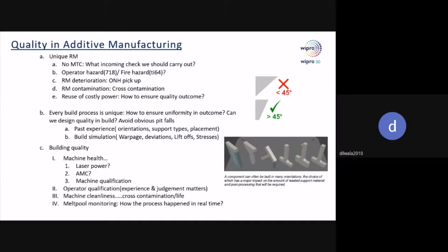Then creating additional supports or placing the parts fully. Like I said earlier, you can fill the build plate with parts fully. What will happen? Then the area of exposure would increase. When the area of exposure increases, there is a possibility that you will get more warpage and more distortion. So you need to be very cautious about how many parts you are placing and what is the distance you are maintaining between each part. If you do that, you will get heavy distortion or warpages and undesirable effects like cracks and delamination.